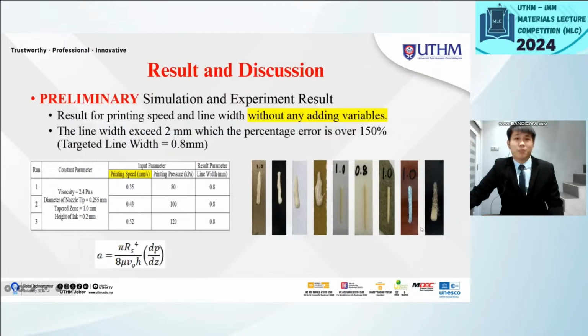For the simulations and experiments, there are three main steps: preliminary, first, and second. The preliminary step involves testing with the existing mathematical model. The first step incorporates the substrate surface energy variables, while the second step includes both substrate surface energy and ink surface tension variables. Starting with the preliminary step, the result indicates that the line width exceeds 2 mm with a percentage error greater than 150%, whereas the target line width is 0.8 mm. This demonstrates that the current mathematical model is inadequate for these conditions and requires modifications.